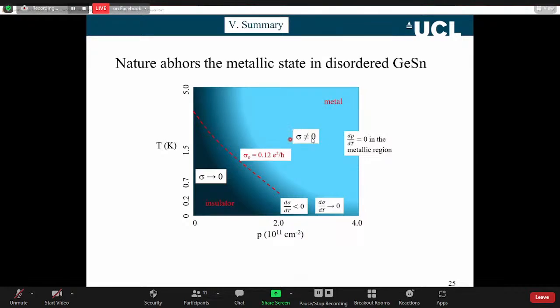We have a conductance which is not zero, but it's got a thermal activation to another edge. Change in the carrier density with temperature is zero. We don't lose carriers. There's no magnetic freeze out. Carrier density is set by the doping level, what they call gate voltage. We have this very, very clear minimum metallic conductivity given by the very, very close to the Mott value. So it behaves in a sense like a textbook ordered system.